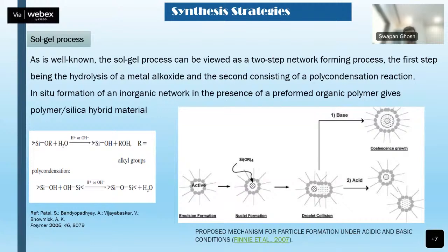Coming to the sol-gel process, this is a very well-known, common process. In the sol-gel process, basically there are two steps. The first step is the hydrolysis of the different metal alkoxides, which are used to form the final inorganic particle. And the second step is the polycondensation of these reactions, of the alcohol that we produce. However, critical is that on the right side schematic, if you look at it, there is an active ingredient, for example a fragrance, a corrosion inhibitor, some odor removal agent, or maybe some other chemicals which we really want to have inside a matrix.